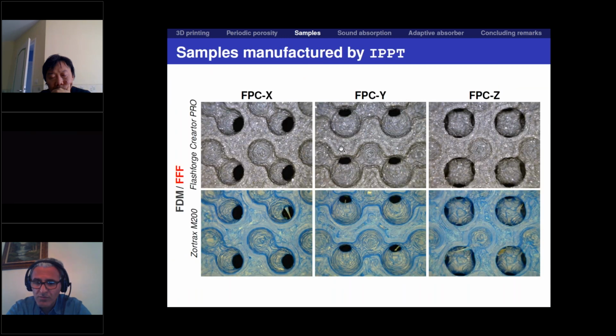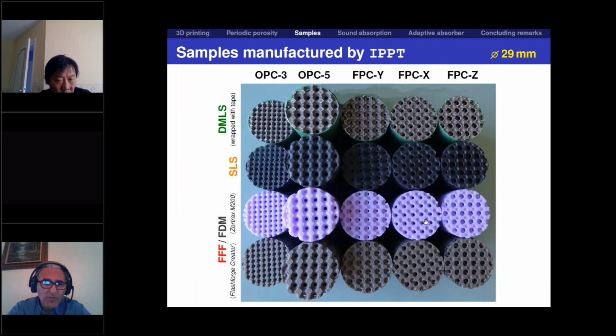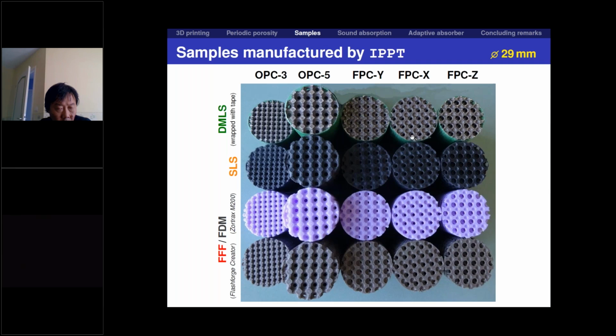So here you may see the top faces of the samples. My PhD student, Kamil, printed using FlashForge Creator Pro. I used Zortrax M200. You see that perhaps the surface of the samples of my PhD student is a little bit smoother than my samples. But anyway, we also manufactured samples using selective laser sintering from polymer powder, also from metal powder, and some resin samples which are not presented here.